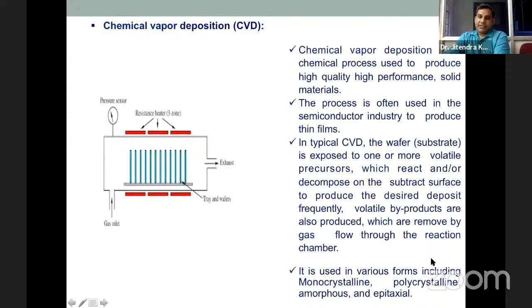So it is used in various forms, including monocrystalline, polycrystalline, amorphous, and epitaxial coating over the surface. In typical CVD, the wafer is exposed to one or more volatile precursors. We use the precursor gases, and those precursor gases react over the surface. Due to that particular reaction, the surface is chemically changed. That's why it is called chemical vapor deposition. So what type of precursor gases we are using is very, very important.